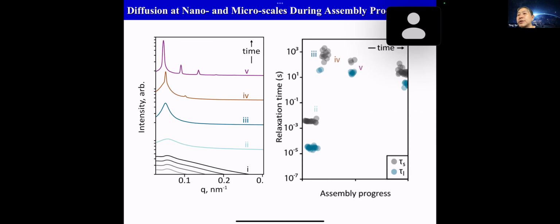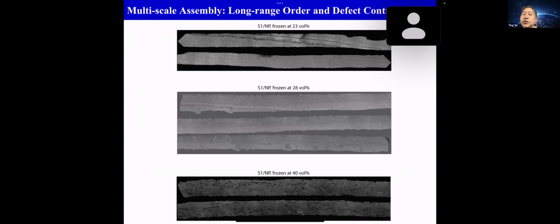But what is also interesting is that even after the nanostructure forms, you see the relaxation time begin to get lower. This is surprising because the solvent is continuously being evaporated, but the system appears to have a higher mobility. And this is where we believe that this interlayer sliding motion is becoming important. We have some data to look at this anisotropy, but we just have to analyze it. But nevertheless, all this data really helps us to program how we should process this material.